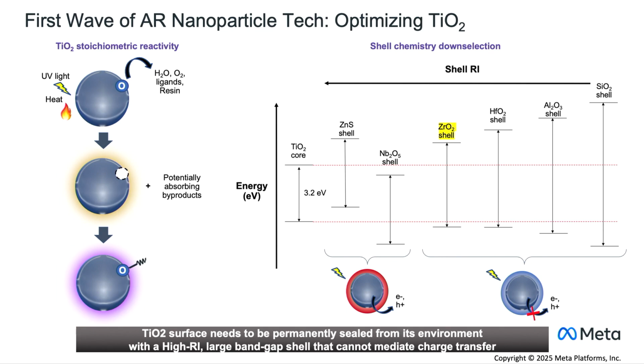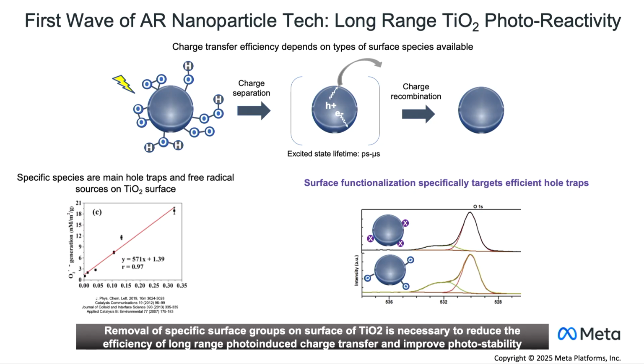We want to find something that fully hugs the band gap of the titania core so that it doesn't act as a cascade for charge transfer, maybe makes it an even more active photocatalyst. So from that work, it's pretty clear that we need to work with our vendors to make higher quality zirconia shells around our nanoparticles, make them as compact and as thin as possible so that we don't lose too much refractive index. The long-range reactivity of these materials, on the other hand, was a little bit harder to understand.